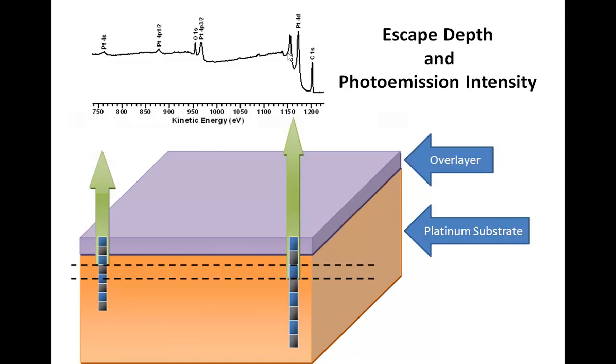However, when we actually try to do this, we find that the spectrum, when measured, does not produce peaks in the proportions that we expect based on the photoionization cross-sections. The photoionization cross-sections are an important part of understanding the relative intensity of these peaks, but the instrumentation will also influence the relative intensity of these peaks.